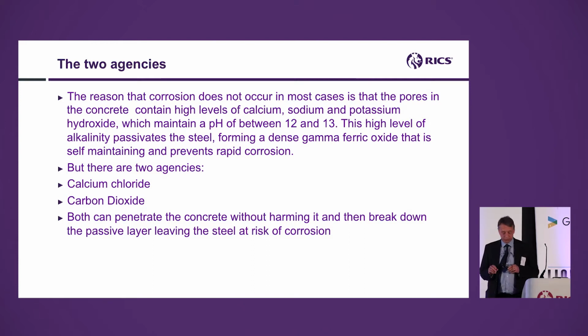And there are two things that are likely to have a pop. Actually, there's more than two, but two main things that are likely to have a pop at it. The first one is one of the most common gases in the atmosphere, carbon dioxide. And that in solution will attack the passive layer and disturb it. And when it does that, the concrete is at risk, or the steel is at risk of corrosion.